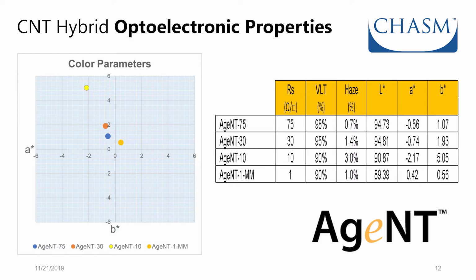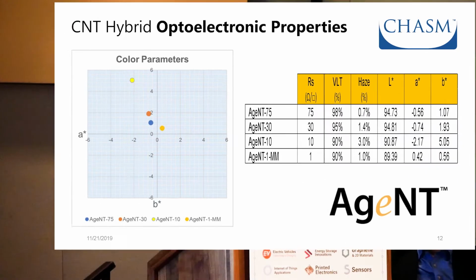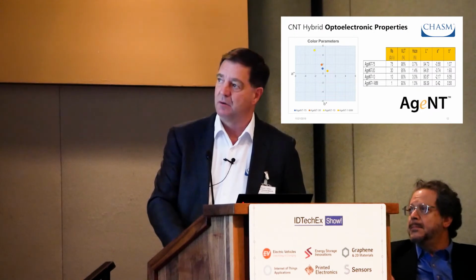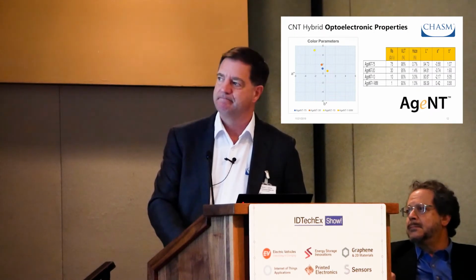But our haze values are respectable, 0.7%, 1.4%, and then when we get up here for the higher loading of silver nanowires, 3%. Color parameters, our materials, the AgeNT-10 has enough silver nanowires in it that it is more yellowish in color, but the other materials have pretty low amounts of color. And this is an advantage over other printable material like PEDOT.